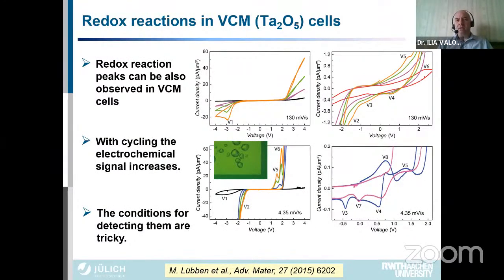So I explained in the previous slides a bit more about the electrochemical metallization memories, where metallic filaments are formed, and metallic ions from it are responsible for the switching process. But in the VCM, in oxygen change memories, in ReRAM or valence change memories, you also see electrochemical reactions. This time they are often related to oxygen, which is typically used or extracted from the solid electrolyte material, or naturally absorbed moisture or protons, which are almost unavoidable in most of the preparation processes and steps during the preparation of the devices.